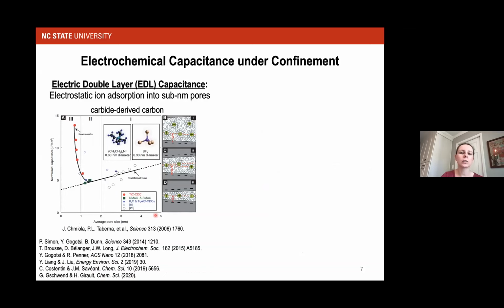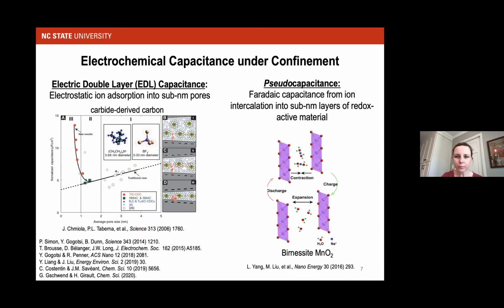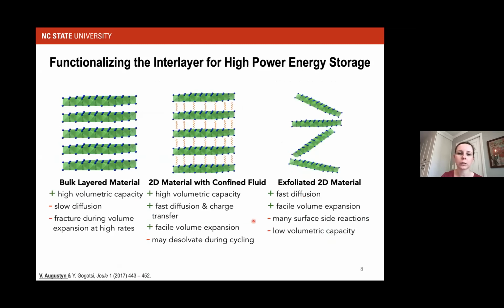So for example, how does the double layer form on a high surface area carbon? This is a classic paper from Yuri Gogotsi and Patrice Simon showing this increase in the capacitance when the cation size approaches the pore size of the activated carbon, as you have this squeezing of the double layer. On the other hand, if you come to this picture from the intercalation chemistry standpoint, this no longer looks like an electrostatic response, but rather looks like an intercalation reaction. And that's this idea of pseudocapacitance that has been used to describe the particular response of birnessite manganese oxide in aqueous electrolytes. And I'll talk a lot about this in my presentation today.